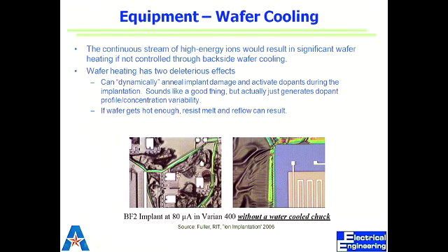Okay, now this is what we were talking about, cooling. During implantation, it gets heated up. We have to cool the wafer also during that process. That's done by what we call backside cooling. If we don't, this is what's going to happen to photoresist. You see all these cracks and deformation in the photoresist. And this is the case where there's no deformation because we cool it from the backside.